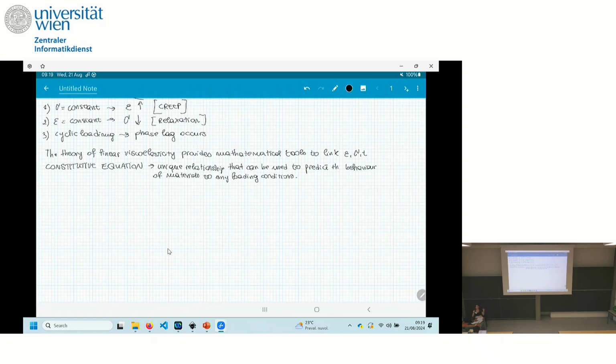We will see you can use these springs and dashpots, and it's going to work really well in the spectrum where you fit. But as soon as you ask your model to predict outside the spectrum, it's going to fail completely. So basically it's going to work really well in that specific spectrum that you fitted.